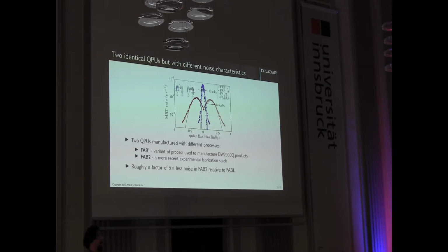The width of these spectral features, so you can see there's pairs of peaks, red and blue respectively. These are tunneling processes where we initialize a single physical qubit in one of its wells of the double well potential, and we measure the rate at which it leaks across to the other side. And we do it in the opposite direction, hence the pairs of peaks. One's going from left to right, and one's going from right to left. With the blue peaks here, they're pretty much right on top of each other, but there are indeed two peaks in there. It ends up that width is related to T1 processes. So those relaxation or excitation processes are going to happen when you're exchanging energy with the environment. It's a measure of the integral of the noise spectral density at relatively high frequency. So you can actually go from here and back out T1s if you wish.